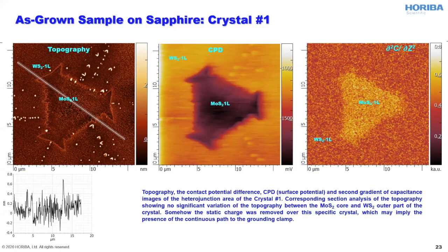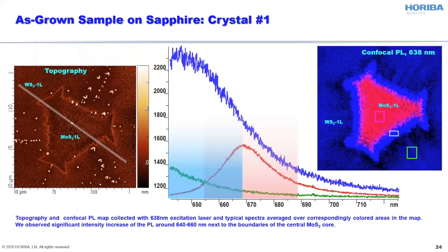So first, we characterized this structure with conventional confocal microscopy, and we collected a quite nice confocal map. We see that along the junction line between the molybdenum disulfide core and tungsten disulfide shell, there is a transition area that shows quite significantly increased photoluminescence signal.